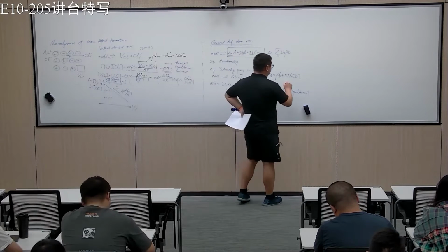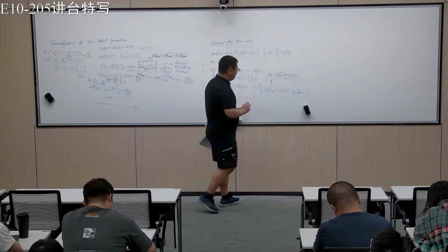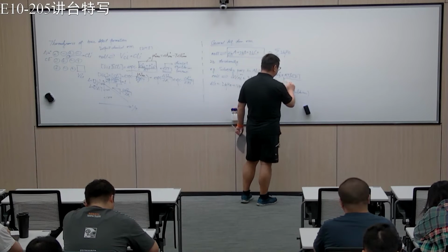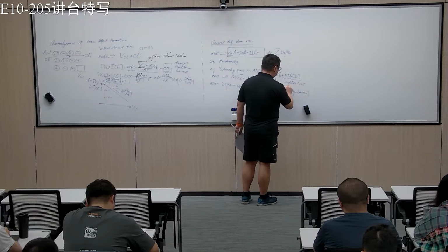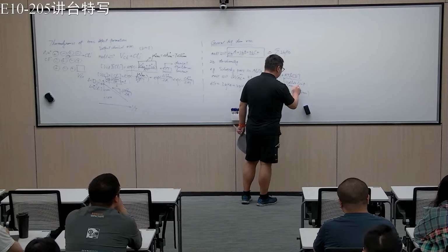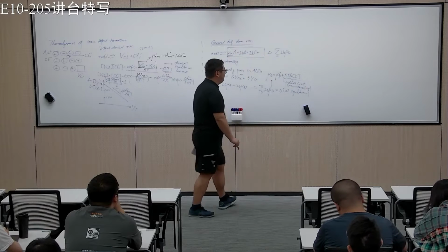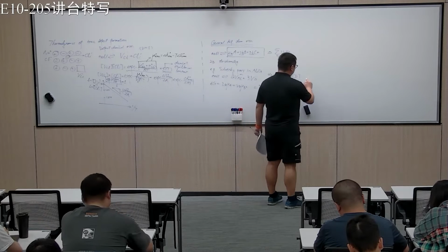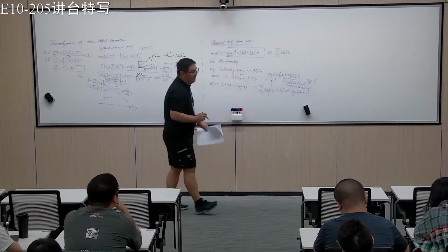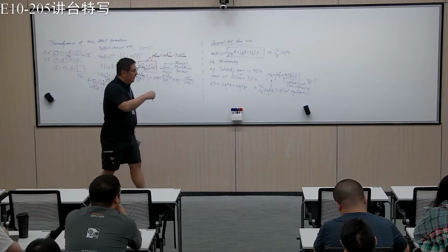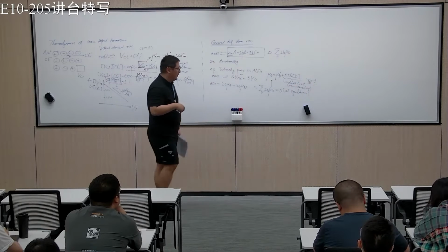Of course, in this case, the reason we can use this, again, I just want to remind you, there's an assumption with that, this basically dilute limit, or it's called non-interaction. So basically what it's saying is that the gamma is basically 1, gamma t is basically 1, which means that the activity coefficient for each defect is basically 1.